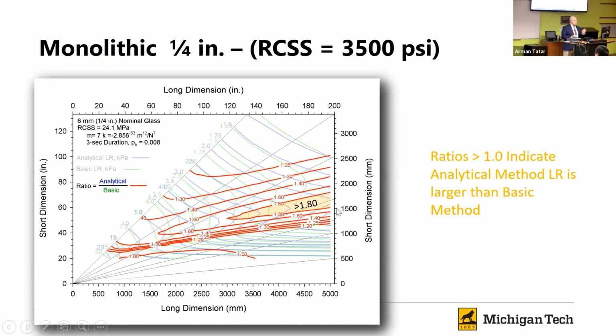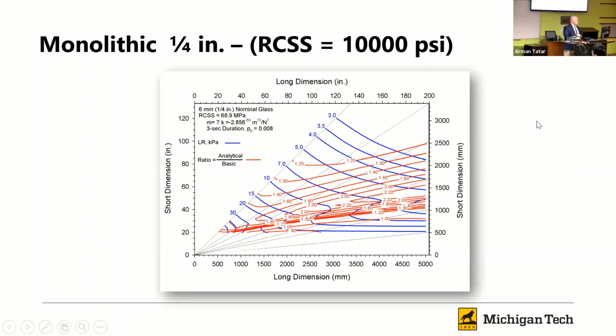I will tell you that even with this increase, the glass is actually still stronger than this estimates it. But we've definitely narrowed that gap a little bit, and we have it now in a way where it's actually a function of RCSS, because we're going to find when we do fully tempered glass, the minimum RCSS there is 10,000 PSI. Now, when they make heat-treated glass, the people that run those machines do a great job. It's truly an art form to get those to work properly. And for heat-strengthened glass, you can't dial them in super precisely, so they're going to be a little bit above that minimum because they want to make sure they don't have a piece that comes out that slides below the minimum, right?